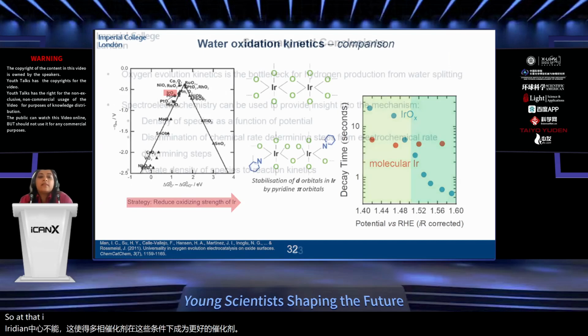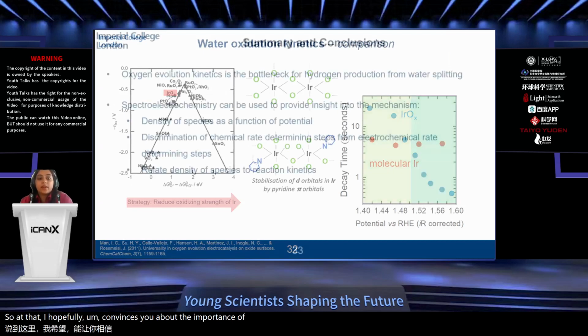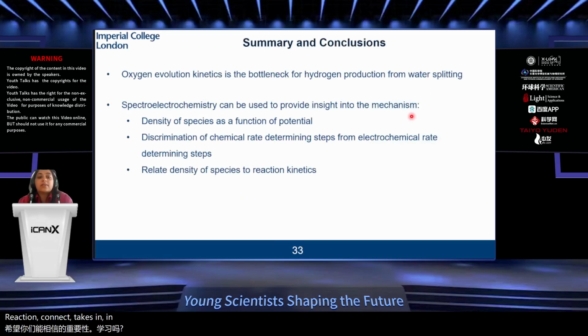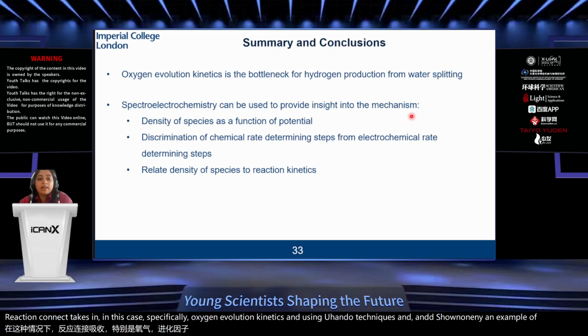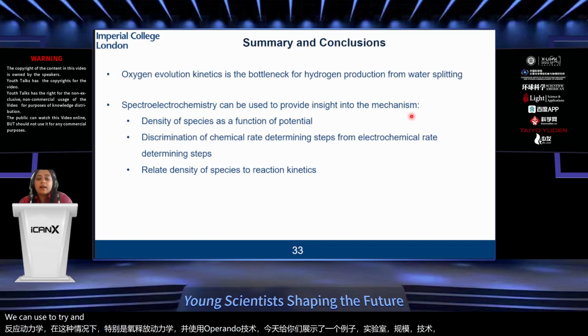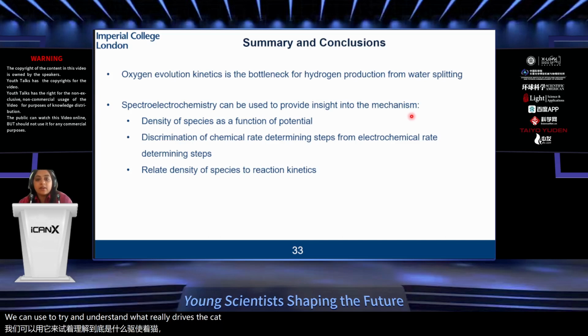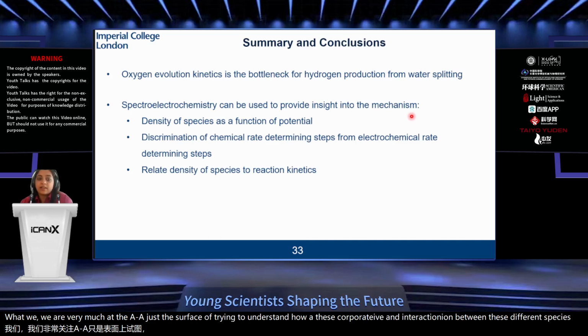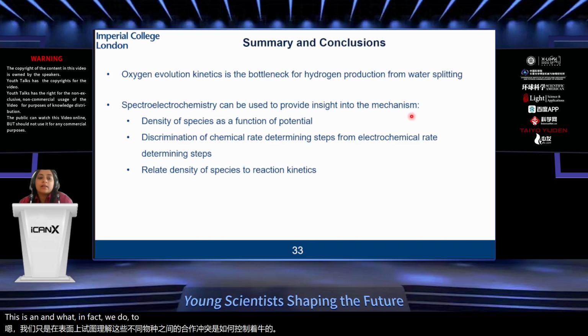So with that, I've hopefully convinced you about the importance of studying reaction kinetics, and in this case specifically oxygen evolution kinetics, and using operando techniques. Today I've shown you an example of one lab scale technique that we can use to try and understand what really drives the catalysis on some of these different really interesting materials, and how we can start thinking about relating the density of the species that we form to the catalysis of the reaction. We're very much at just the surface of trying to understand how these cooperative interactions between these different species govern the catalysis, and what in fact we can do to start really tuning these long range interactions to